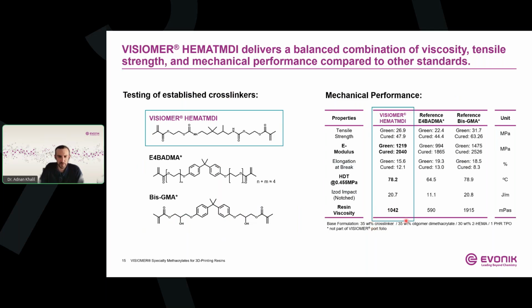the formulation containing the HEMA-TMDI sits in between the two different materials. While it exhibits somewhat higher viscosity than the E4BADMA, it remains significantly easier to process than the highly viscous BISGMA system. More importantly, this good processability is also achieved without compromising the performance. The cured HEMA-TMDI formulation reaches an HDT of around 78 degrees Celsius, matching the performance of the BISGMA and significantly exceeding the performance of the E4BADMA reference.